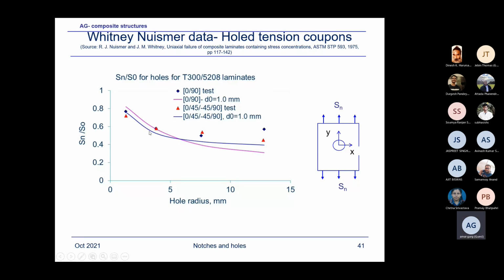As you can see here, it is matching, but as the hole size increases, it is deviating. That means for these predictions to match with the analysis, you might have to tweak the D naught value. So it seems that D naught for these ones is higher than D naught for this one. Depending upon that, one has to calibrate the D naught value with the hole radius, and that's what is shown here. So probably the D naught varies with the hole radius.